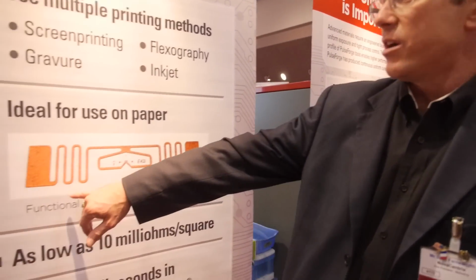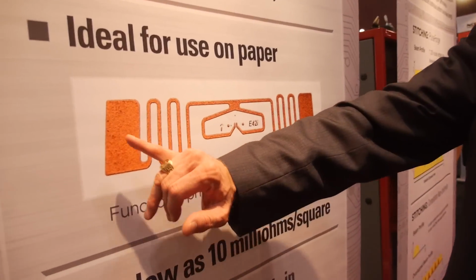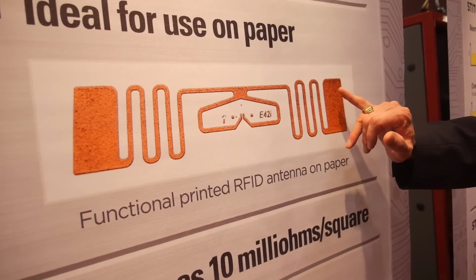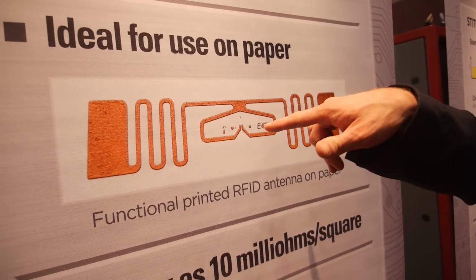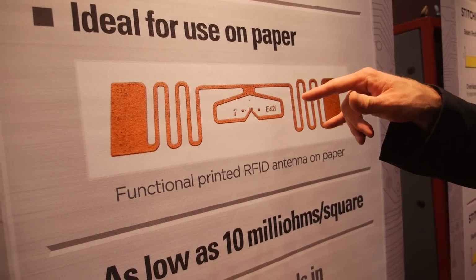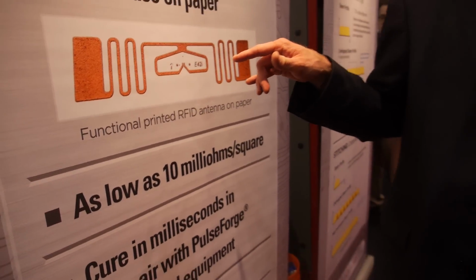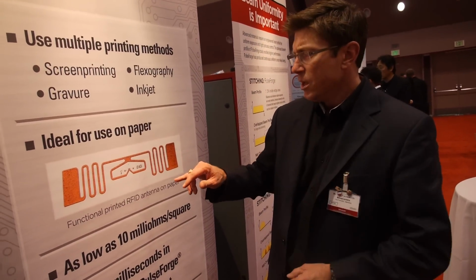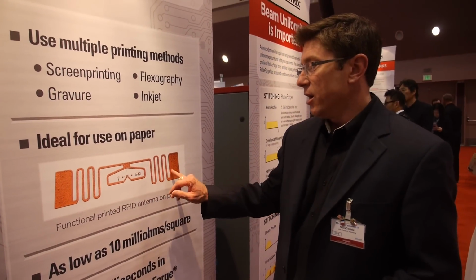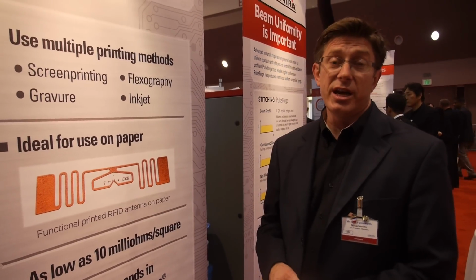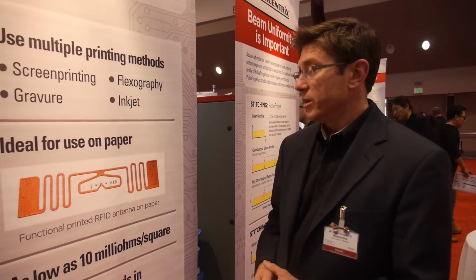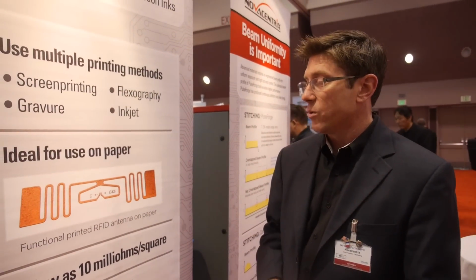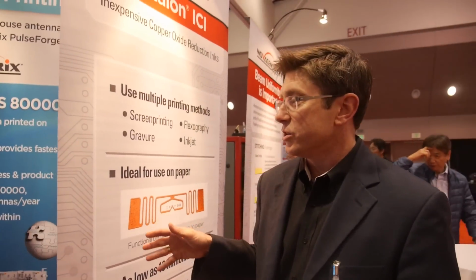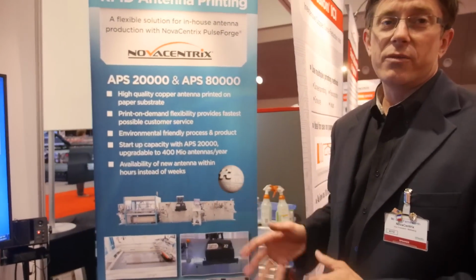And when we look at an actual application like this RFID antenna, what we see here is incredible uniformity. We could measure the actual sample and see that sample to sample to sample, the repeatability is within a fraction of a percent. But also visually, we can just do a quick qualitative check, and the quality of the image is quite uniform. This is an application that we're doing with Mühlbauer for RFID production.